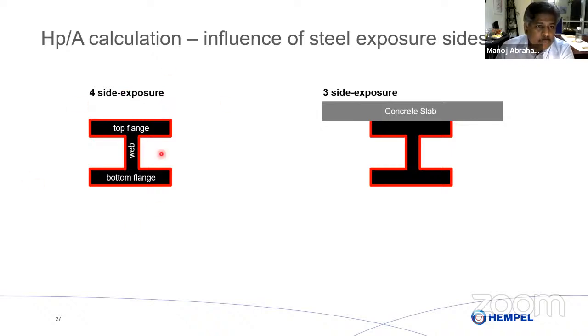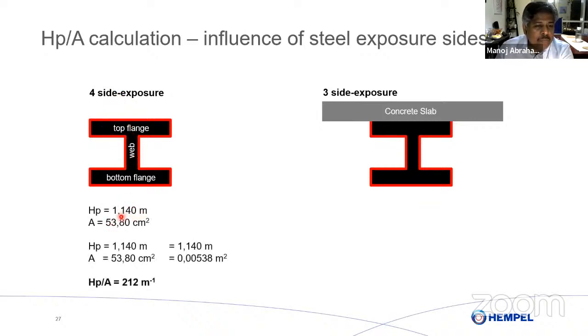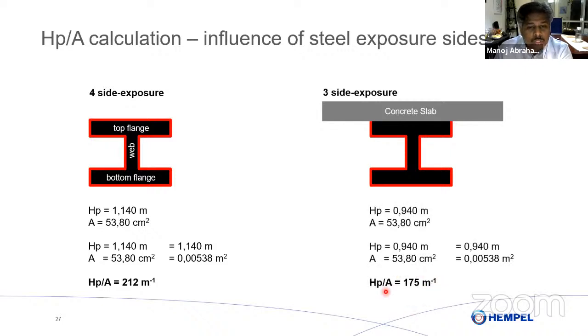So this is a four-side exposed column, okay? So all four sides fire can come. So it is called four-side exposed, and this is the area. The heated perimeter is 1.14 meters. The area is 0.0053 square meters. You divide the heated perimeter by the area, you get 212. The same section, it's got concrete on top, so that means there is no heat coming in. It's only three-side exposed. So what happens? Your area remains the same, but the perimeter reduces. Therefore, you have a lower number. So in this situation, I can apply slightly less thickness here. I have to apply more thickness here.